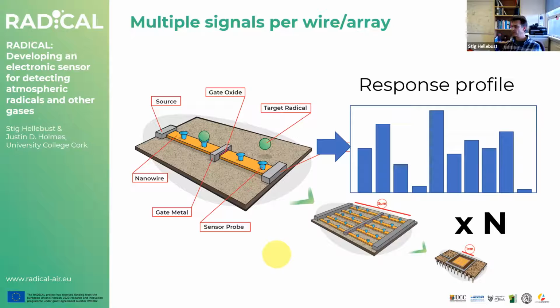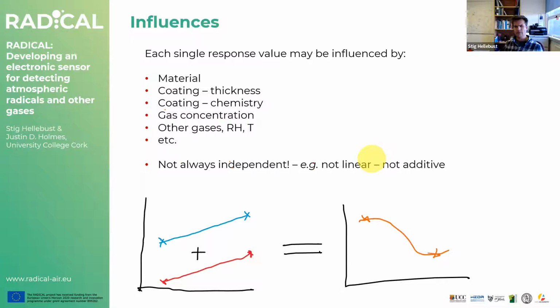So that's great, but the issue then is that any one of these signals, like I said, depends on the shape of that curve that we measure. When you increase the concentration of something, that will change a lot of those features, but not necessarily in a linear way. The effect it has on the different features is not necessarily additive. And then you have interferences with other gases and environmental conditions, temperature, all of that. So it's not just the chemistry of the interaction that determines that signal. And it's also not given that a higher concentration just extrapolates in the same direction of that signal. So these are all things we have to figure out.